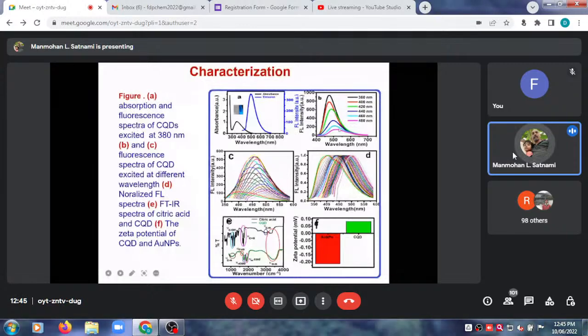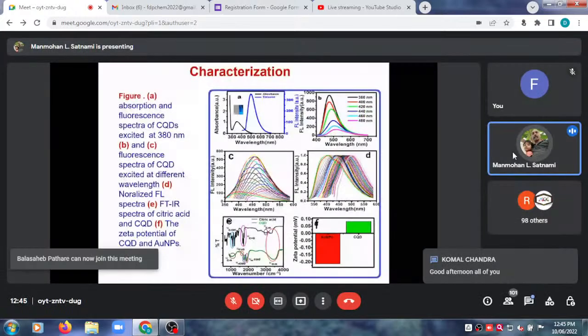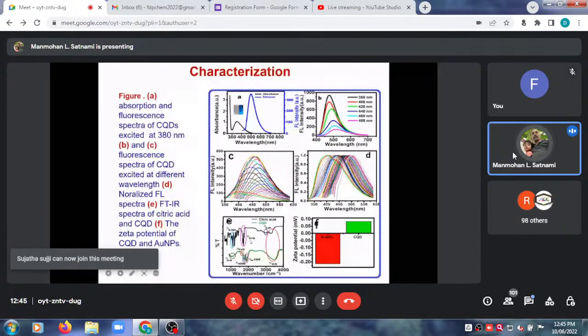This is the FTIR spectra of carbon quantum dot. Through this, we characterize the surface of carbon quantum dots, meaning what different functional groups are present on the surface. So you can see from this figure that the carbonyl group, carboxylic group, and somewhere hydroxyl group are present.